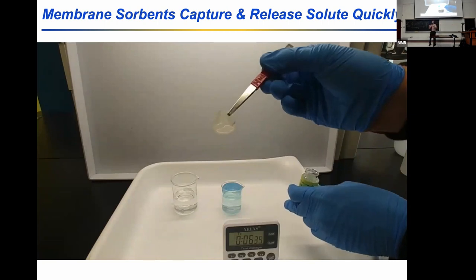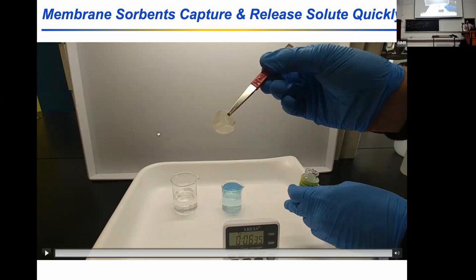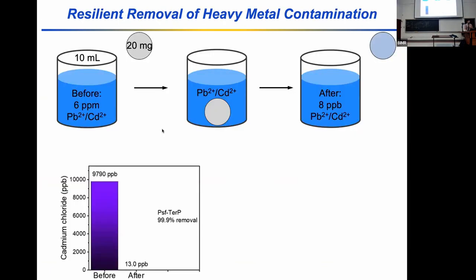So this ability to regenerate and reuse the sorbent is attractive. We were able to regenerate and reuse this material 50 times before the student graduated and decided that 50 cycles was enough. So it's very attractive in terms of the ability to manipulate the Langmuir isotherm and regenerate and reuse.